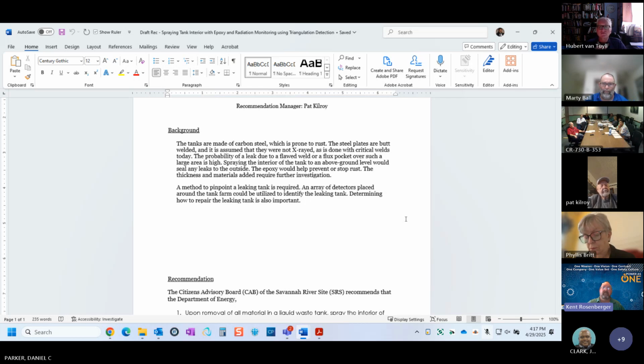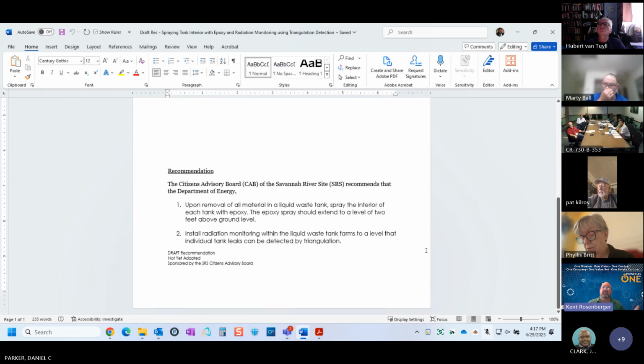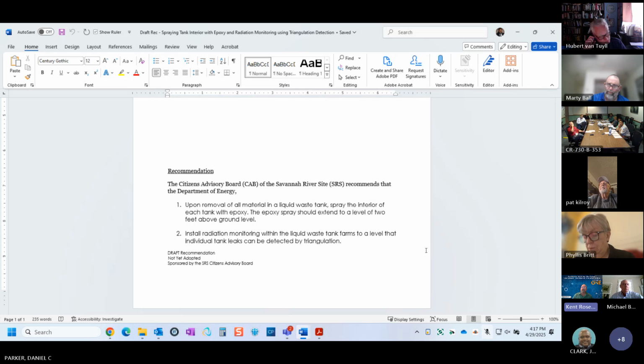If we go into the closure mode, the reason we haven't gone to anything similar to what was added in the recommendation is that once the tanks get filled with grout and the annuli get filled with grout, in most of those cases, you have cementitious material on both sides of that carbon steel. Cementitious leachate for a long, long time is a pH of greater than 11. So when the tanks get filled with grout, it's almost better than what we deal with today, which is an active system that requires actions on our part to ensure that it maintains those conditions. After closure, it's actually a passive condition because any liquid that might get into the tanks and get through the cementitious material will be conditioned such that the pH is of a level that the tanks won't corrode.